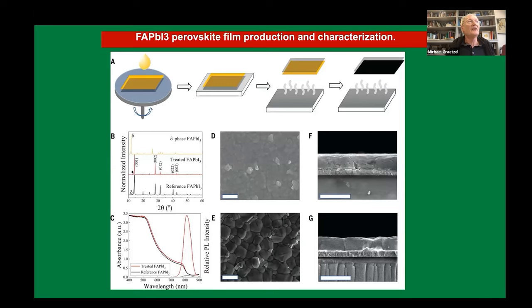When we submitted our paper to Science, the referees came back rather harshly and said: show us that it's not the methylammonium — we claimed the thiocyanate was the main stabilizing factor, but the referee said we had published ourselves that methylammonium also works, so show that it would also work with formamidinium thiocyanate. We went back to the lab and lo and behold it did work also with formamidinium — so it was clear that what caused the stabilization was the thiocyanate anion, not the cation.